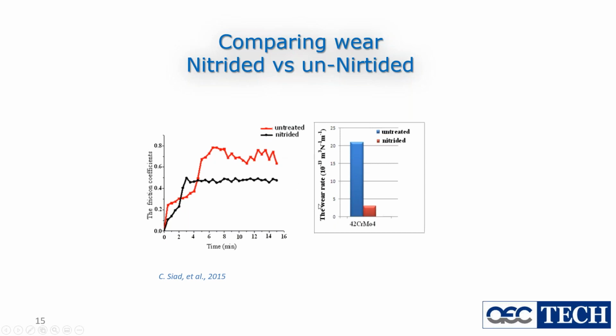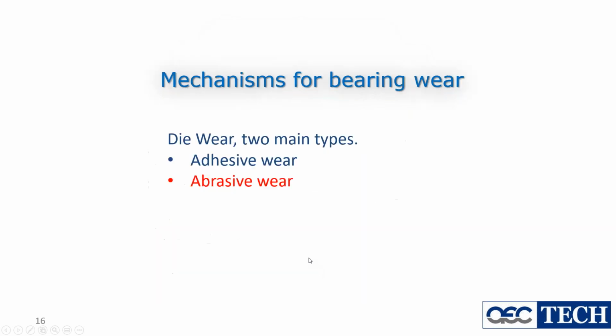And then you can see the wear, in terms of material removed from the surface of the die made of 42CrMo4, is about 21 versus 3, maybe 7 times more wear in the untreated versus the nitrided die. So the nitrided die can last maybe 7 times longer than an untreated one.